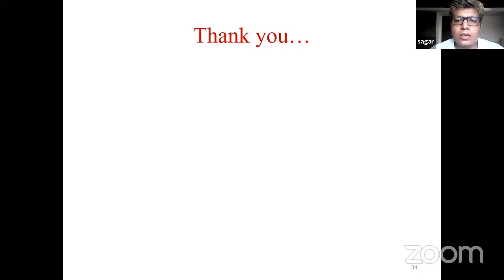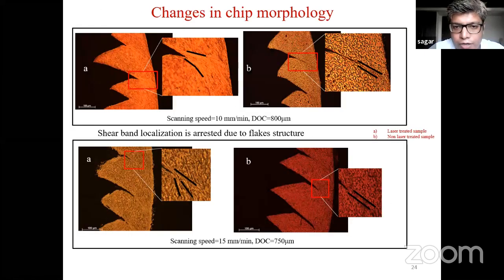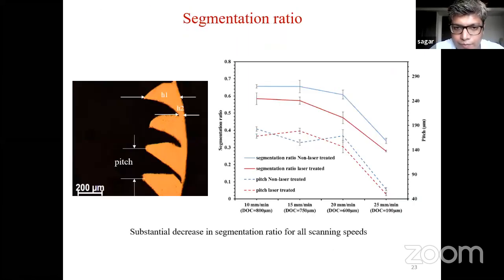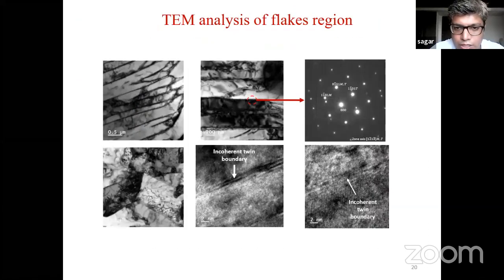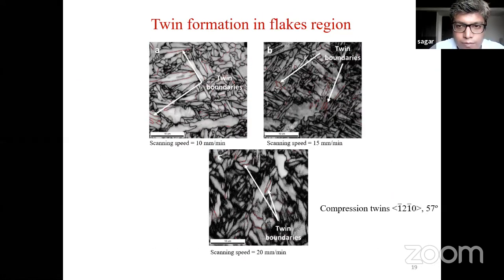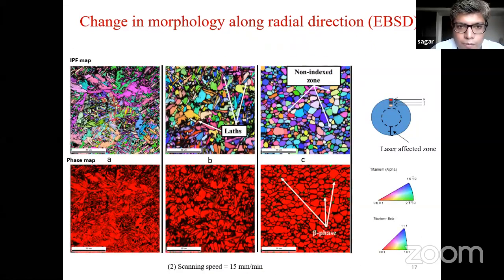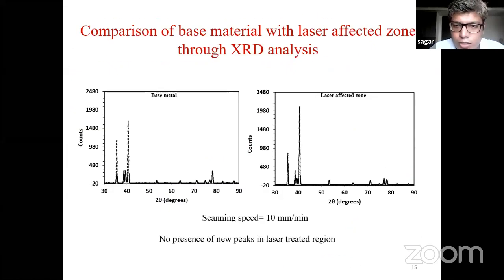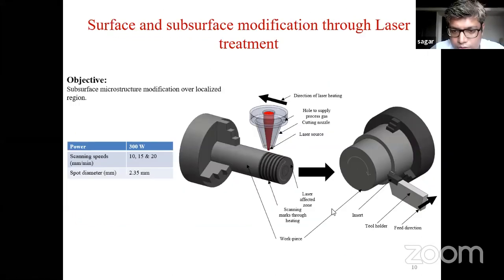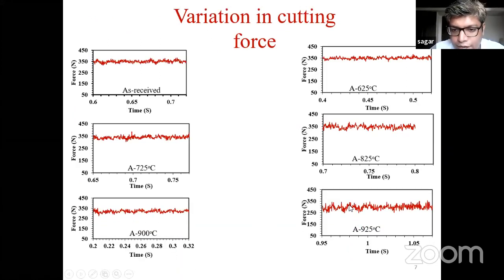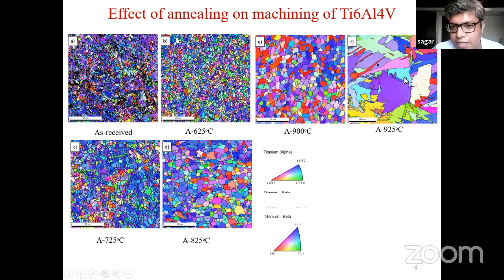So grain size will not affect machinability for every material. I was talking especially in terms of titanium. Here you could see the cutting forces. The variation was quite higher when I was performing the machining on the sample which is annealed at 925 degrees Celsius, and that sample has the highest grain size.